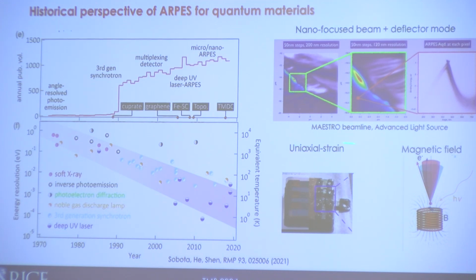So what's shown here, I took it off the website of the MAESTRO beamline, which is a nano-ARPES beamline at the Advanced Light Source in California. This is a real space scan with ARPES. This is the real space dimensions, and then this is a zoom in. Here the step is 20 nanometer steps with 120 nanometer resolution. And then for each pixel on this real space scan, you can do the full three-dimensional measurement in momentum space of the band dispersion here. So this is a new mode that can be utilized. I'll say a few words about that in the next couple of slides.